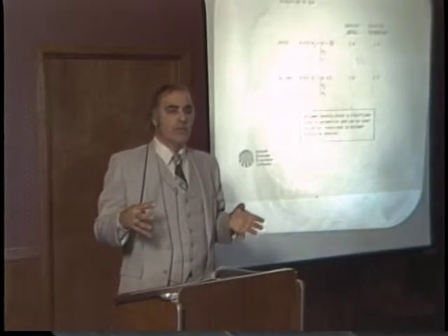If, of course, this were a more polar system, we would expect a higher permeation. So what it implies is that we have filled the void area with more material. There's more weight per unit volume in the polymer. Consequently, it restricts the ability of materials to intersperse themselves through that polymer network, thereby reducing the permeability. Next slide, please.